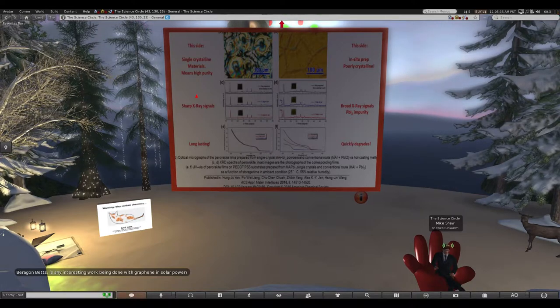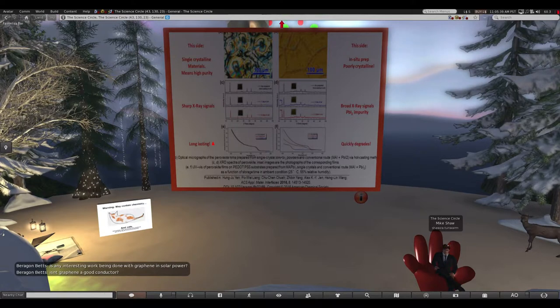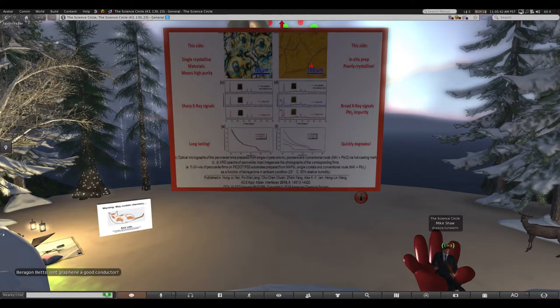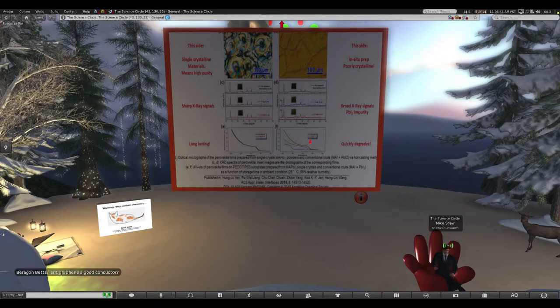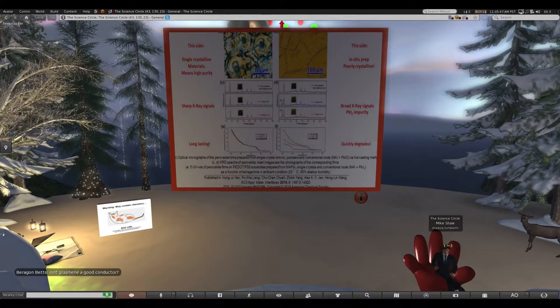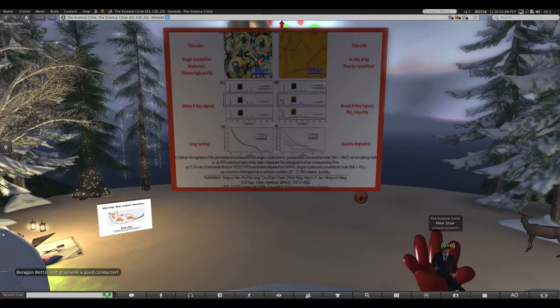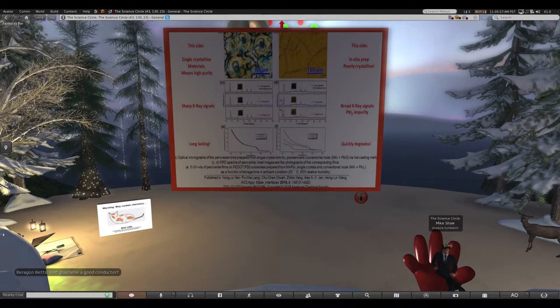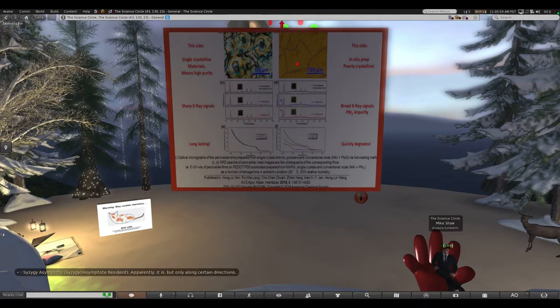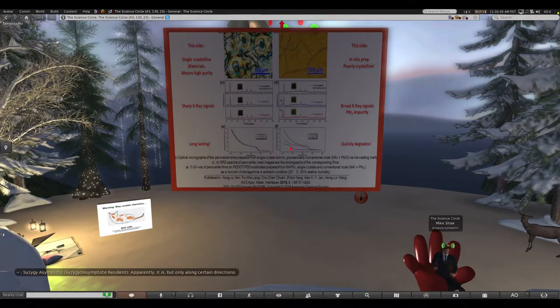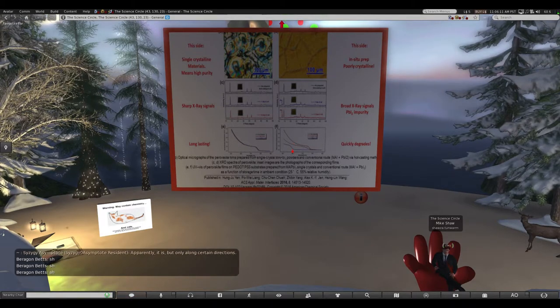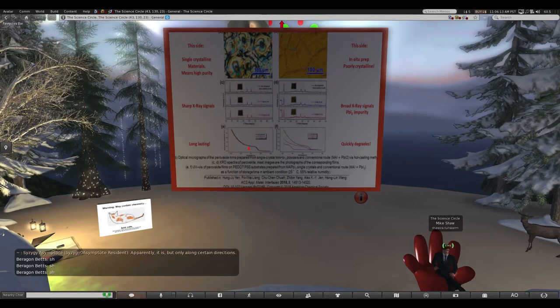So on the left, it's the data for the pure materials. On the right, it's comparable data for stuff that was just slopped together and cast in situ. You can see the difference in just the photographs in the top row. Pure materials give you lovely crystalline patterns. The impure materials give you slop, and the slop doesn't last nearly as long. This bottom row, F, shows degradation over just a few days, whereas E, the pure materials, give you less degradation.